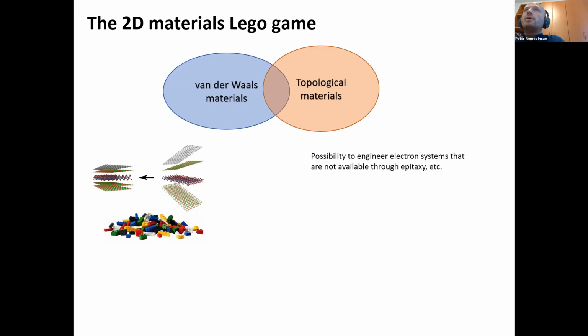So basically, the real power of 2D materials lies first of all in the fact that there is this whole zoo of them with very different properties. But it could be argued that an even larger advantage of these materials is that you can use them as Lego bricks, as André Geim has introduced, that you can stack one on top of each other, and you can do this stacking in a way where you can achieve configurations of 2D materials which are basically not available through any other means. So it's very hard to grow materials on top of each other sometimes. And you can make stacks of these 2D materials in atomic configurations which are basically not available through a thermodynamic path.